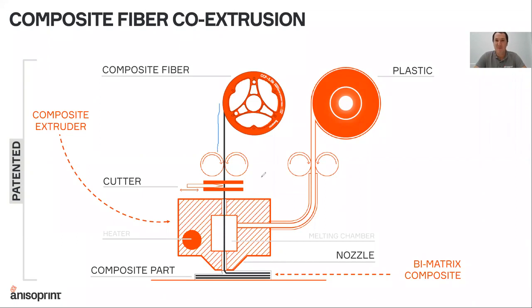One input is for fiber material. So fiber goes straight from the spool into the hot end, into the melting chamber. And there is a separate channel, a second input for plastic material, that goes inside the melting chamber, and it mixes with the fiber in situ during the printing process. And there is just one output, one nozzle, where the mixture of the fiber and plastic, so basically the plastic which is reinforced with the fiber in this process, is deposited on the print volume, and the bi-matrix material is formed.